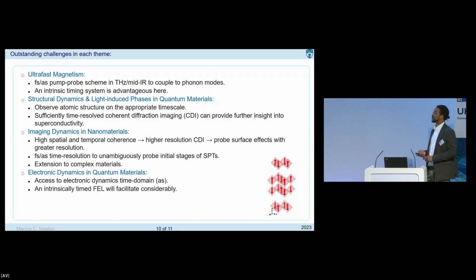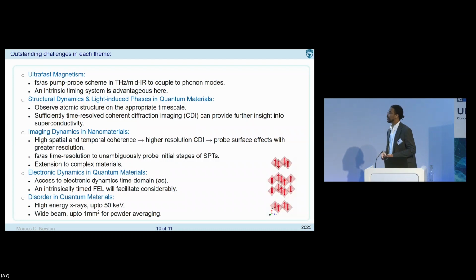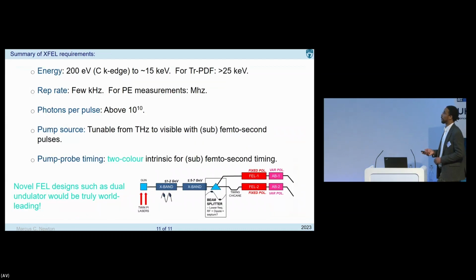For electronic dynamics in quantum materials, access to electronic dynamics on the attosecond timescale is the key thing here. And an intrinsically timed FEL would again facilitate this. And for disorder in quantum materials, using PDF measurements, we want something with high energy, so up to 50 keV, and a wide beam as well, up to 1 millimeter squared for powder averaging.